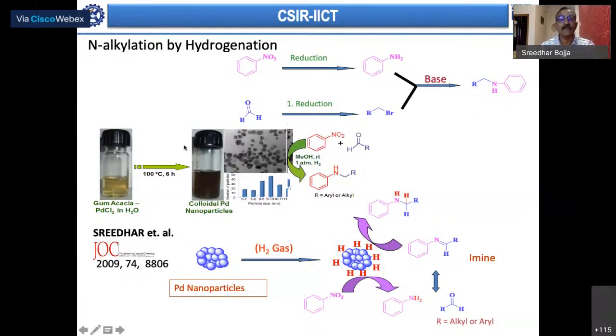But in this technique, what we did was take these palladium nanoparticles in methanol at room temperature with hydrogen as an atmospheric balloon. Then these are the starting materials, and you get the desired material without generating any waste. You could separate the catalyst from the reaction, and we could do this for a few cycles and so on.